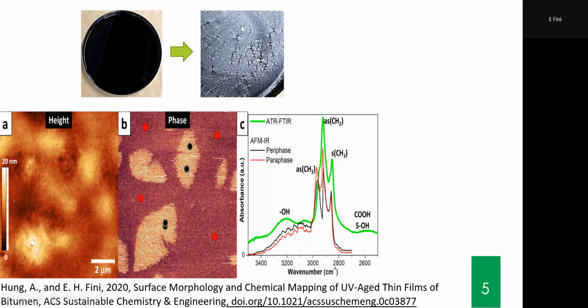So what you actually see on the surface here on the top, the picture I showed you first, it shows you the surface, but it doesn't tell you the whole story about the entire material. So if you think about the bitumen being a few microns, or in this case, we have a thin film. On the top, we have different characteristics as shown with this FTIR. The black and red are on the top surface, and the green is the bulk, and you can see they are very different, surface and the bulk.